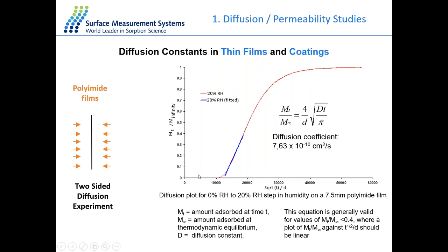We can start the experiment first from 0% RH here, and then expose the sample to a certain level of relative humidity. In this case, it's 20% relative humidity. And with the equation from Fick's law, we can get the mass at the equilibrium state at 20% RH, and also the thickness of this film sample. From the slope of this fitting line, we can then calculate the diffusion coefficient of this film sample at a certain relative humidity. In this case, it's 20% RH, the permeability or the diffusion constant of the film sample.